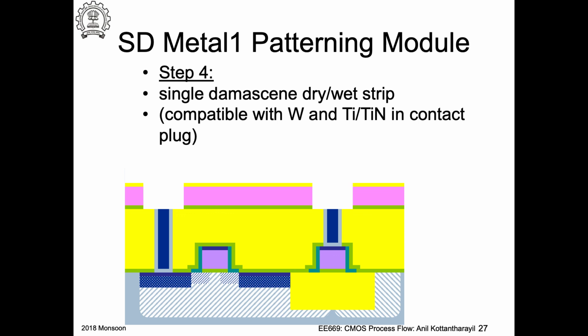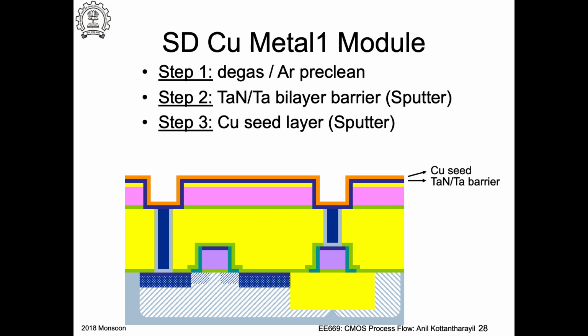Okay, so now I am going to put metal on top. So I would do a pre-clean argon sputtering to remove any oxides that have grown on your tungsten. Okay, and then you put a tantalum nitride, tantalum barrier. Again, you can see this tantalum nitride is deposited. So first you will deposit tantalum, and then tantalum nitride is deposited, so that it actually acts as a very good diffusion barrier against copper diffusion into the transistor regions. Yeah, so you're putting multiple layers of diffusion barriers. Very important.